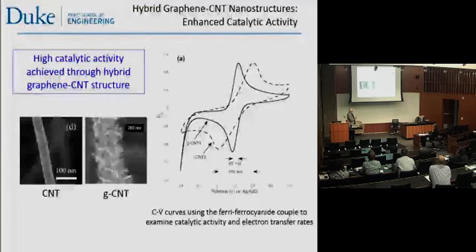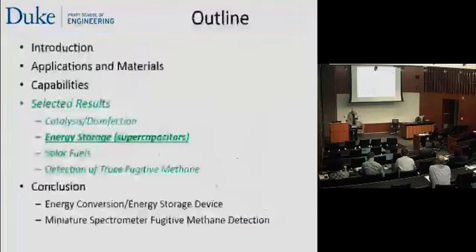So when we look at a current voltage plot on this, you can see the carbon nanotubes, this redox couple has quite a bit of separation, 376 millivolts. Whereas when we use this graphinated material, it goes down to almost the theoretical limit, which would be about 59 millivolts. So that means it's the most reversible, the fastest reaction it can be. So just by adding this new component into the framework that we had before, we've got not only ultra-high surface area, but we've got ultra-high reactivity and reversibility.